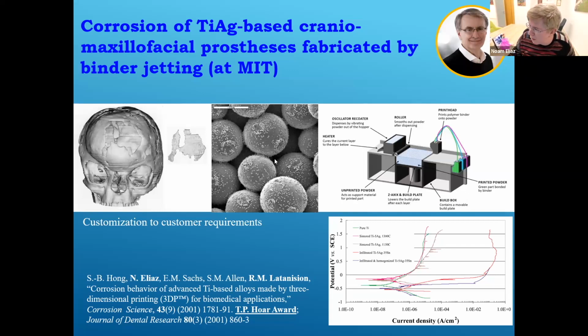You can see in the center the kind of powder that we were using, titanium powder, and what you see on top of them are fine, solidified droplets of silver. At the time, we, as others worldwide, thought that silver would be fantastic for antimicrobial behavior, but in recent years, as the clinical data started to come up, it's now questionable, and there is a debate in the clinical literature whether, for instance, silver nanoparticles should be used at all.